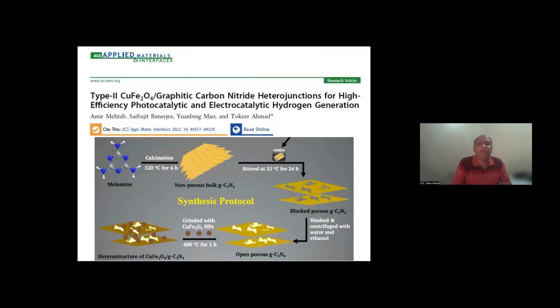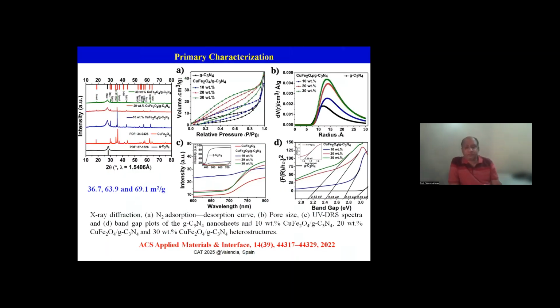Then we have taken these graphite carbon nitride nanosheets to mix with copper ferrite nanoparticles to make the type 2 heterostructure formation of copper ferrite with graphite carbon nitride. We have mixed the graphite carbon nitride with the copper ferrite in 10, 20 or 30 weight percent ratio. This is the synthesis protocol for making these binary heterostructures. So the primary investigation and the primary characterization is very important. And if you have a very good understanding of X-ray diffraction, you can index each and every phase of any kind of heterostructure.